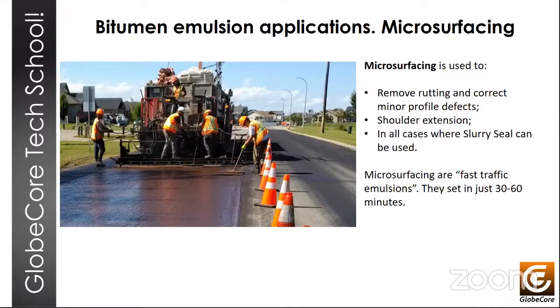When the repair is completed, traffic can be resumed in about 30 minutes. However, for 1 hour, driving speed should be limited to about 40 kilometers per hour. Both slurry seal and microsurfacing imply fairly quick application at a speed of 3 to 6 kilometers per hour, and both technologies allow quick restoration of the road surface. Both act as a protective layer to prevent wear on top of the road and can withstand fairly heavy loads and traffic intensities. Their average service life is about 3 years.